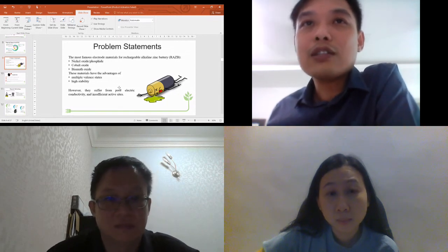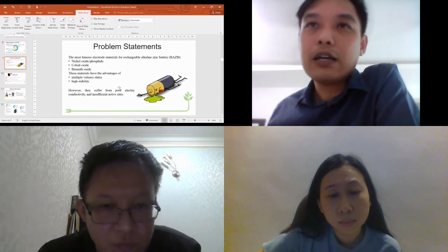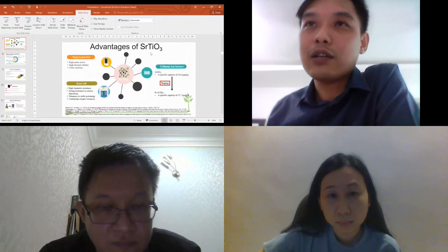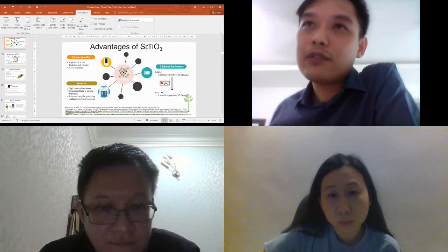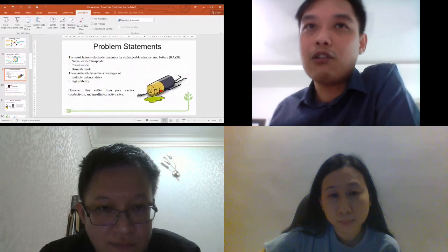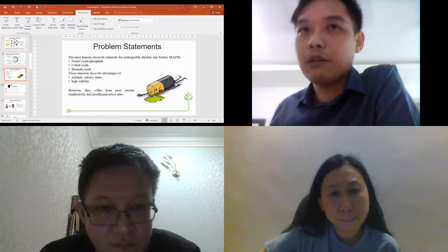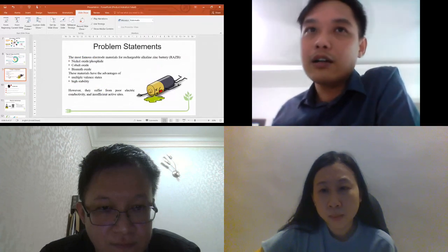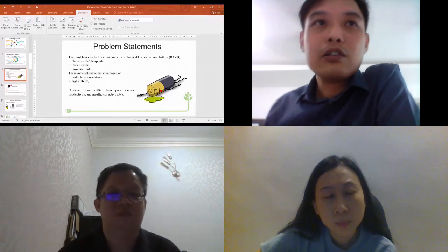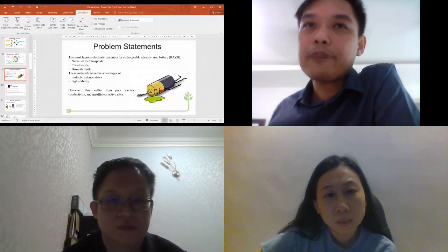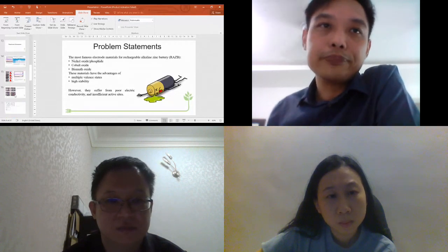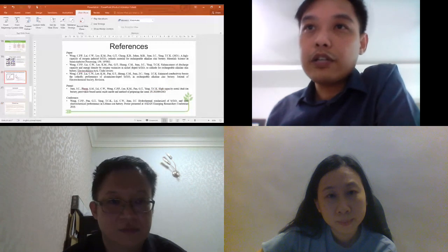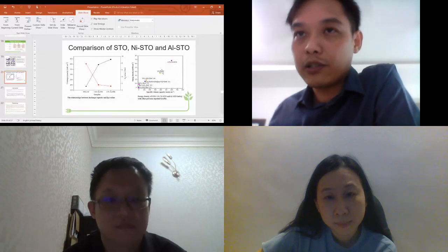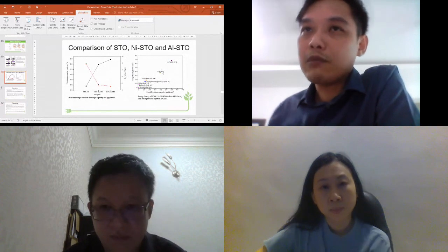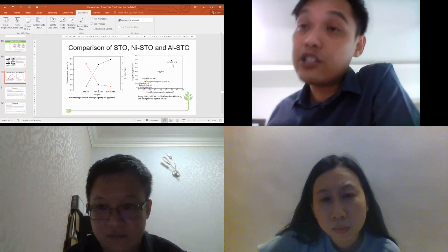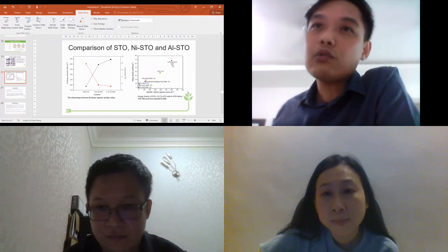So they are using nickel oxide, cobalt oxide, and bismuth oxide. You calculate the cost using the strontium titanate (SrTiO3). This one by itself is almost comparable with nickel oxide, cobalt oxide, and bismuth oxide. Bismuth oxide is not cheap, though. Bismuth is not a very common material, same with cobalt. So in terms of price, it's almost comparable. But in terms of capacity, you can see from our research here, it's much higher, about 2 times higher than currently reported in the literature. So why did we put the nickel here? Because we want to further increase the energy density and also the capacity. So in terms of price, it's comparable.